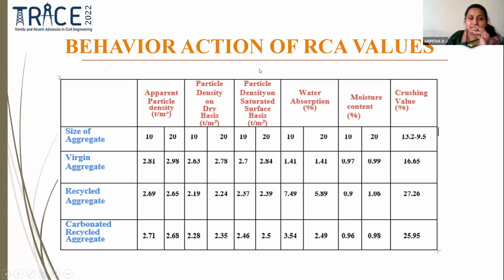Actually, what I'm going to say is, when we are using recycled aggregate, the limit of up to 20% is standard when it is mixed with the other constituents. But when it is the carbon dioxide recycled aggregate, that means conditioned aggregate, what I mentioned as the key factor, this conditioned recycled aggregate acts nearly like the virgin aggregate and gives good strength. That's why we can recommend this carbonated recycled aggregate as per the reference.